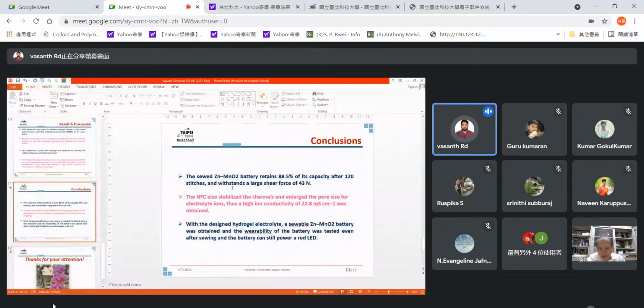And the Zn-MnO2 battery retains 88.5% of its capacity after 120 stitches and withstands a high shear force of 43 Newton. The NFC also stabilized the channels and enlarged pore size for electrolyte ions, and thus a high conductivity of 22.8 millisiemens per centimeter was obtained.